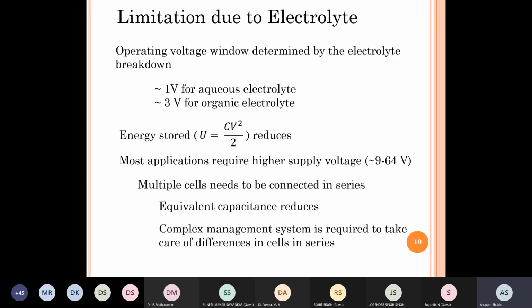So compared to whatever gain is made in the electrochemical capacitor because of higher capacitance, a lot of it is compromised because the electrolyte will not allow more than 3 volts of operating voltage window. So one loses out on this V squared term, and since it is a square term, the effect is much higher. Okay. Now the limitations get further compounded by the fact that most of the applications where we are looking to use these electrochemical energy supply devices actually require higher voltage than a single cell.